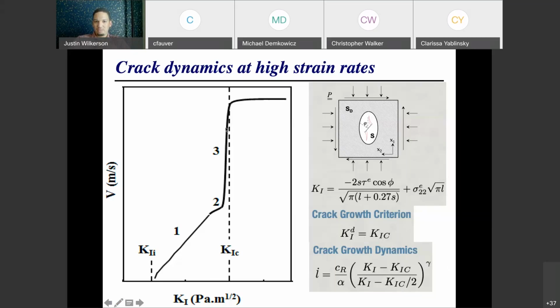So basically, this curve here, we measure the velocity of those cracks in experiments, and then we fit a relationship to that. And this is the relationship that's most often used. Out here in the prefactor, you have the Rayleigh wave speed, and that's going to be the upper limit. As you go to very, very high stress intensity factors, you're never going to drive this any faster than the Rayleigh wave speed. This alpha parameter can be used to drop that maximum velocity down a little bit if that's what your material exhibits. And then here we have the function of this stress intensity factor, which gives us this curve as it approaches the asymptote. Okay.